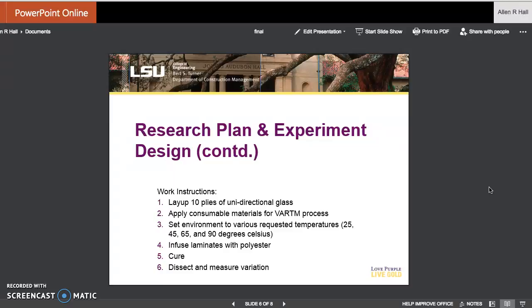And then we're going to set the temperature to various amounts, 25 Celsius being right about ambient, and then 45, 65, and 90 being the max allowed. Infuse the laminates with the polyester resin, let them cure at their different temperatures, and then we will dissect them perpendicular to the fiber to then lay them on their side and measure the deviation from being flat.